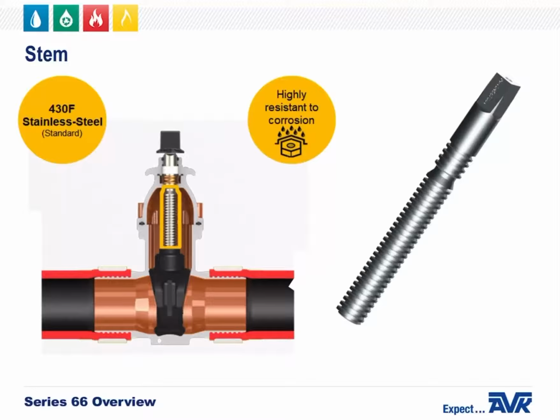Stainless steel stems do not contain lead, zinc, or aluminum, so they are superior to the bronze stems in applications with continuous contact with drinking water. The 304 stainless steel stem offers corrosion resistance approximately equal to that of the 430F. However, the 304 material has a lower yield strength. The 316 stainless steel stem offers corrosion resistance that is better than the standard 430F. However, the 316 material also has a lower yield strength.